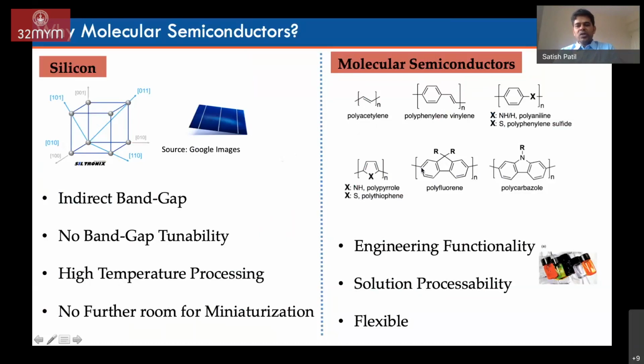You see there is a pi-conjugated backbone. You can functionalize this pi-conjugated backbone with a long alkyl chain. If you put this alkyl chain there, you can easily process these semiconductor thin films in a common organic solvent. That is a major advantage over a conventional semiconductor like silicon, where the processing has to be done at high temperature. And these materials can also be coated on any thin film substrate. For example, you can print essentially on any kind of substrate. So these are the advantages of molecular semiconductors.